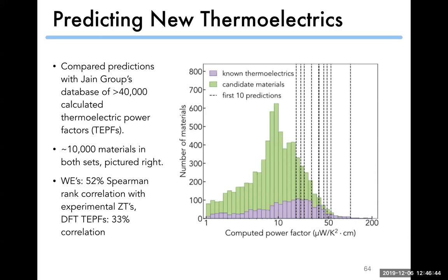does this match up to the experimental values of the actual thermoelectric figure of merit for these materials? So we found another dataset that had a few hundred thermoelectric figures of merit in it. And then a few of these were in all of the sets that we've calculated, or that we've made predictions for with the word2vec model. And we actually found that the rank correlation, so just ordering the materials based on the word embedding similarity to thermoelectric, is a better predictor for the actual thermoelectric figure of merit than just the power factor.